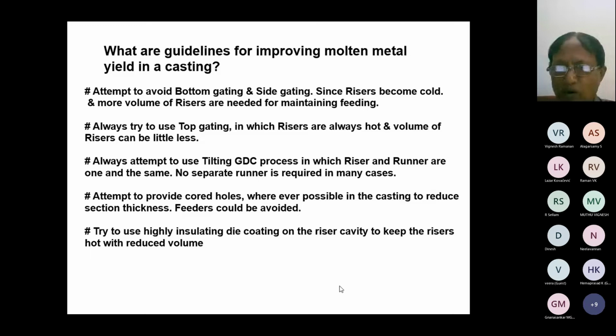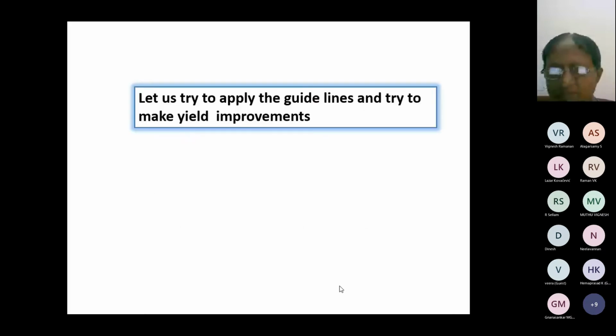Attempt to provide core holes wherever possible in the casting to reduce the section thickness. Feeders could be avoided. Try to use a high insulating die coating on the riser cavity to keep the risers hot with the reduced volume. These are some of the guidelines which will help us to reduce the amount of metal poured. Let us try to apply the guidelines and try to make yield improvements.